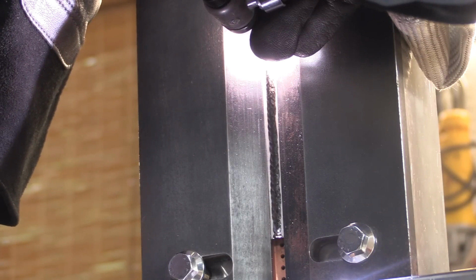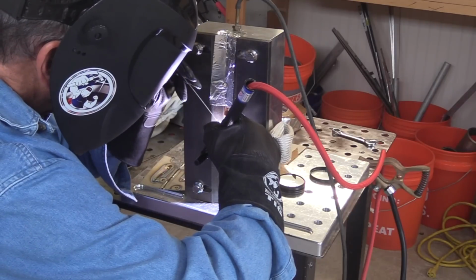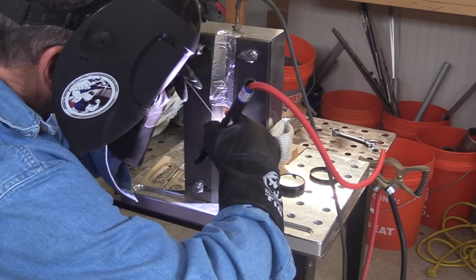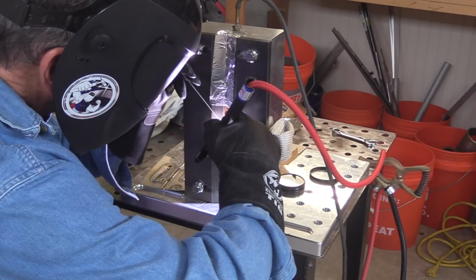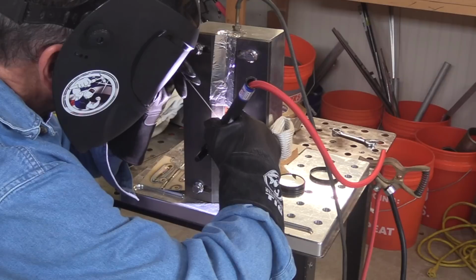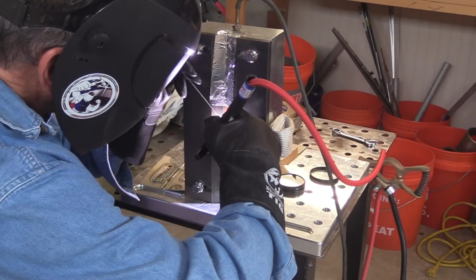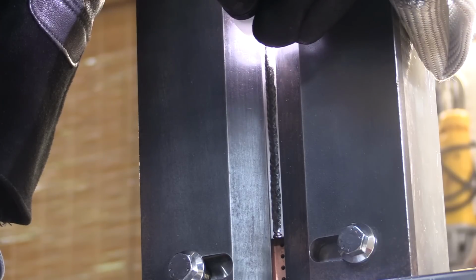Okay, in just a few seconds coming up, I'll be welding into that very end tack. And watch closely when I do this and you'll see why I like to put an extra dab or two of filler metal on those ends. As I come in getting pretty close to that tack, I watch it really closely. I start to back off the foot pedal just a little bit. I watch the front of that puddle run into that tack, and then I start really getting off the foot pedal to keep from melting away that end. And that has worked for me really well on parts as well as tests.